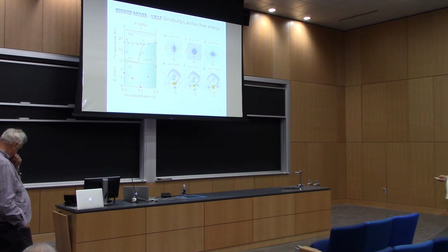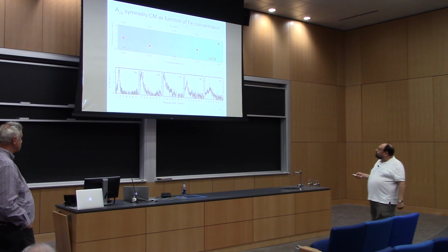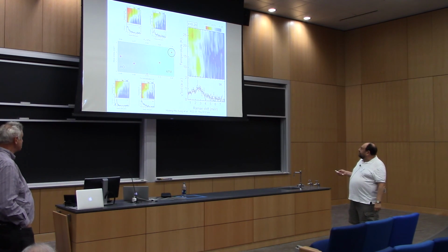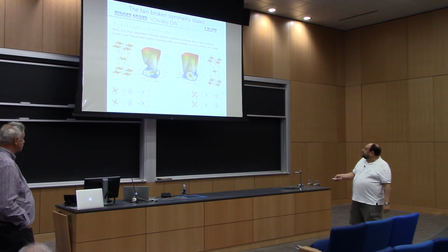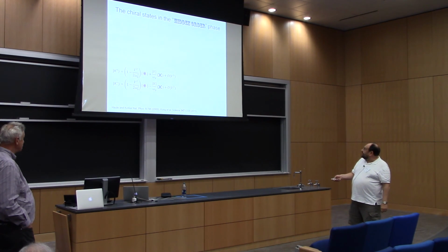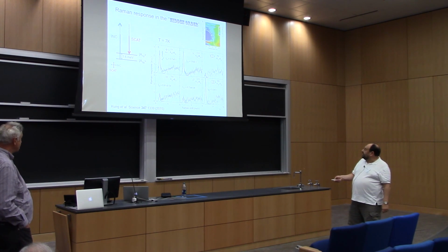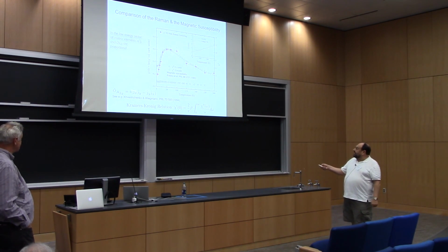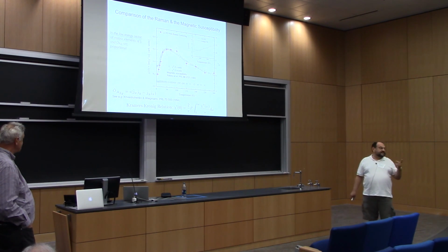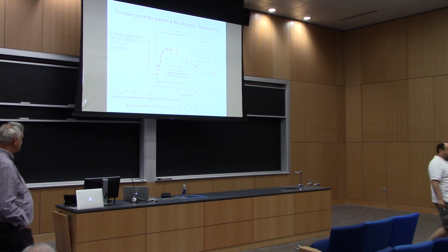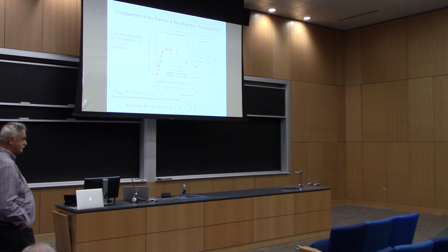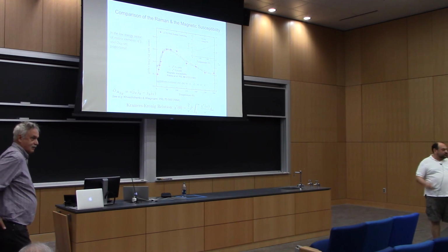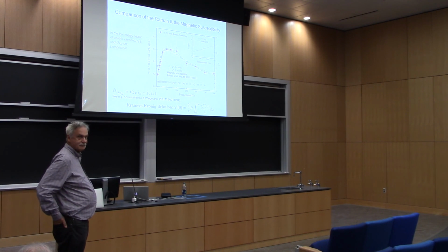So the only mechanism to have this A2G, if I don't need to include spins, is that I need to have an operator that is antisymmetric under the XY exchange. For example, a circular current, like one proposed for high Tc, would lead to that, or something of this kind. The Raman vertex has to induce, at least in an intermediate state, some kind of flux.